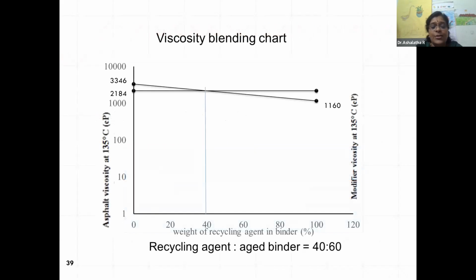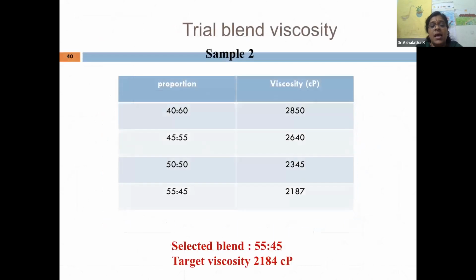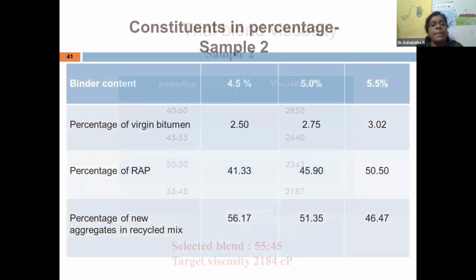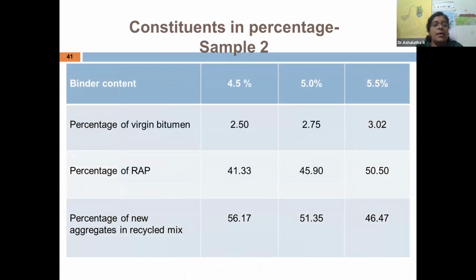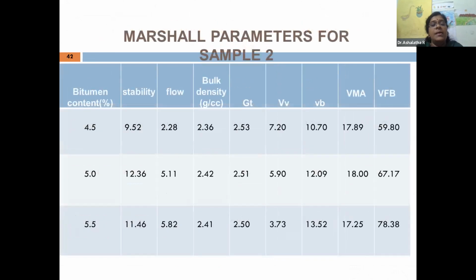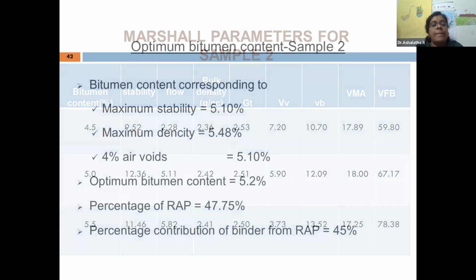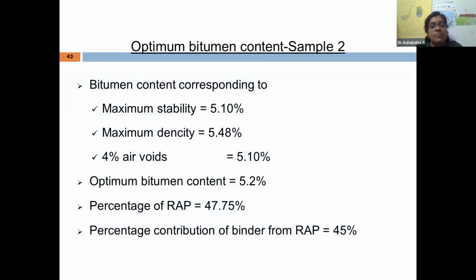So we found the ratio of the recycling agent and the aged binder for the second case, and found which is the best proportion, nearer to the target viscosity. Then, keeping that proportion constant for different binder contents, we found the percentage of virgin bitumen, the percentage of RAP, and the percentage of new aggregate in the recycled mix. Marshall specimen parameters were determined for sample 2 for 3 bitumen contents, and the optimum bitumen content was determined as 5.2%, the percentage of RAP was 47.75%, and the percentage contribution of binder from the RAP was 45%.